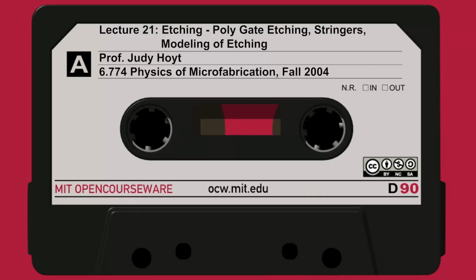In 2010, which is a ways off, we're reaching aspect ratios on the order of 100, and beyond that going even higher. And you notice beyond 100, the cells are all marked red, indicating that in that range, people don't really know yet how to etch such deep aspect ratio, 100 to 1. So new technology is going to have to be developed in order to do that.